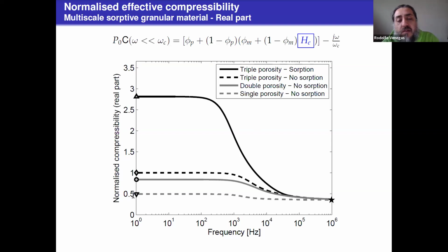So the difference between the low frequency and high frequency value will determine how large the magnitude of the imaginary part is. If this value is equal to the one at high frequency, it means that we won't have any dissipation of sound energy. This is not the case when we consider triple porosity material with sorption, where at low frequencies, we have a very large value of normalized compressibility, and at high frequencies, it tends to the value of a conventional single porosity material where no sorption is happening.